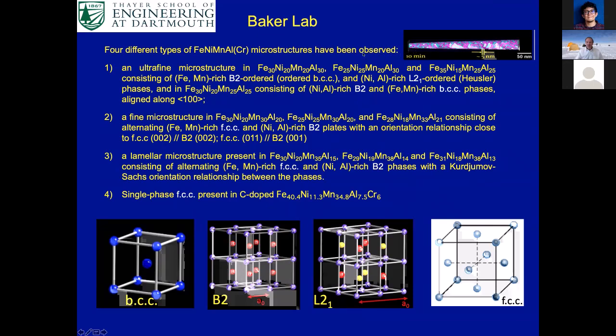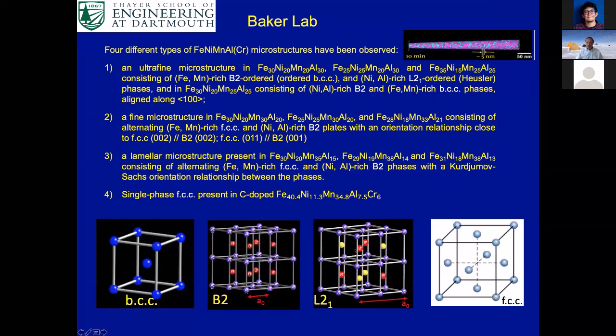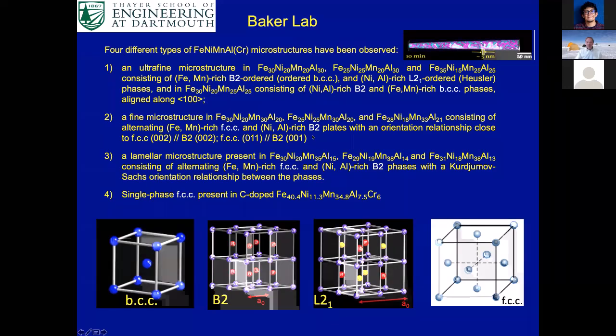And these tend to be somewhat equiatomic iron, nickel, manganese, aluminum, and they consist of B2 and BCC phases, or L2-1, which is a further order in the L2 of the B2 structure, shown down here, L2-1 plus B2. They turn out to be incredibly strong, but quite brittle. Then we actually looked at some alloys where we lowered the aluminum content, and we ended up with an FCC and B2 structure in plate form, with the orientation relationship shown here. They also turned out to be relatively strong, but also not very ductile.